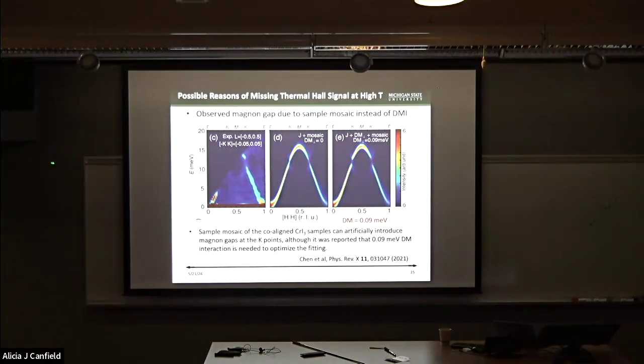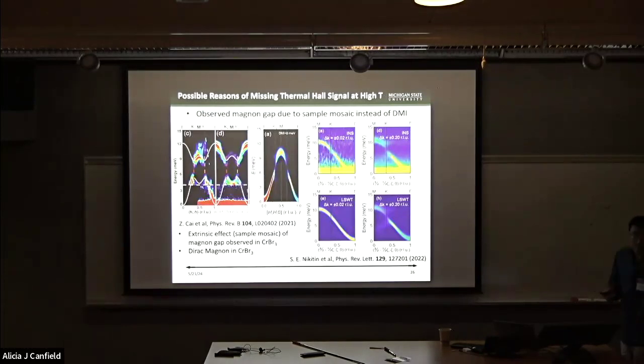This is similar to the experimental data. Okay, but in this paper, they declared that the system still has a 0.09 meV DM interaction, which could benefit the experimental results. So again, the sample mosaic could artificially introduce a magnon gap at the K point. And such a feature has been observed in the sister compounds, for instance, in chromium tribromide.